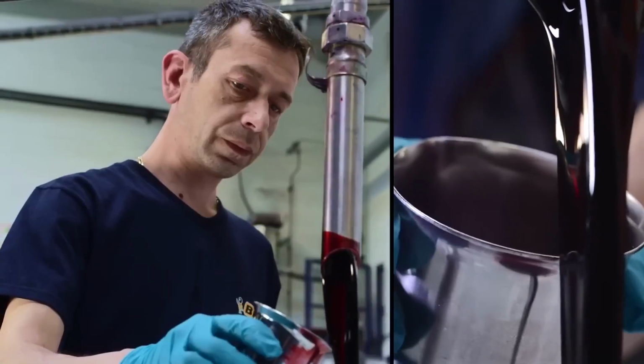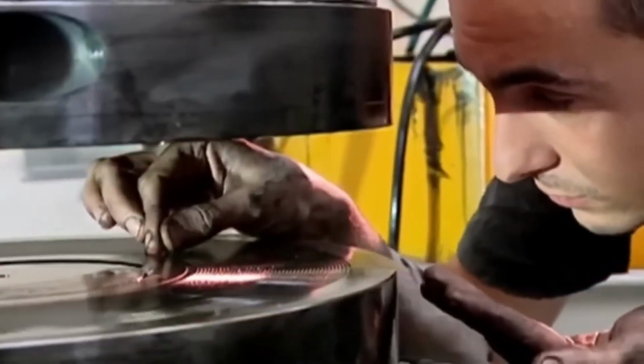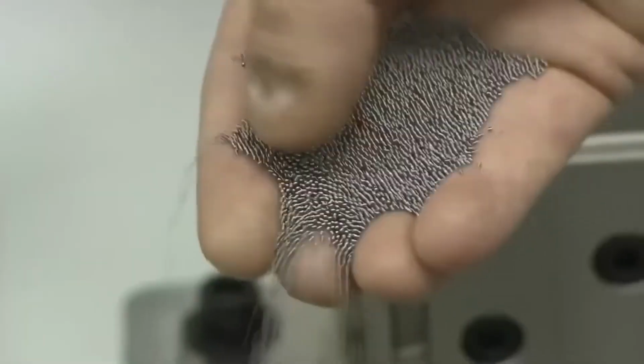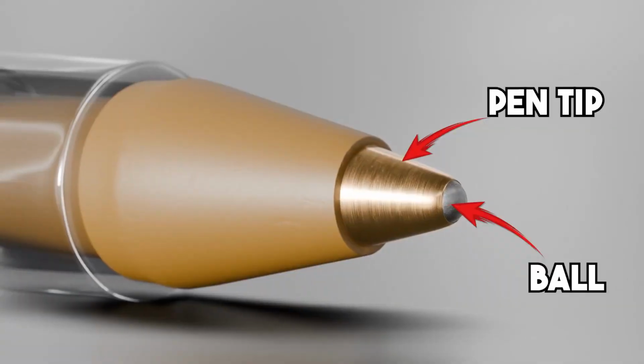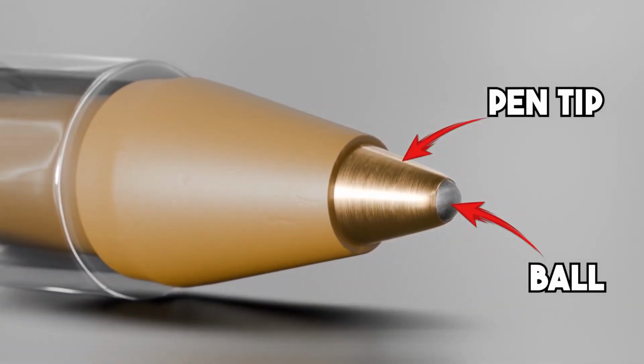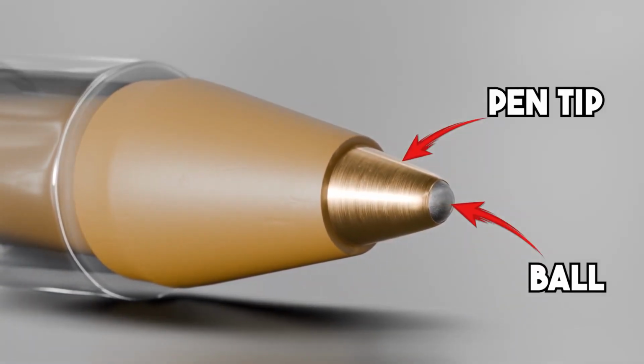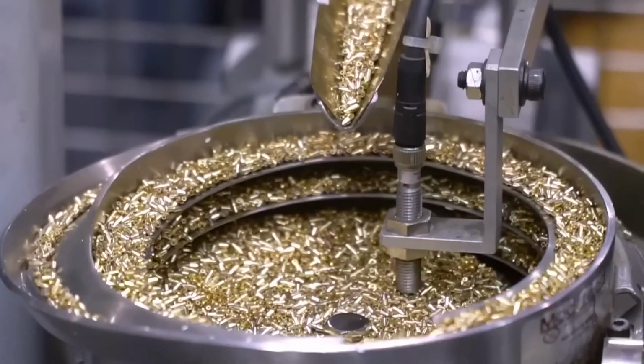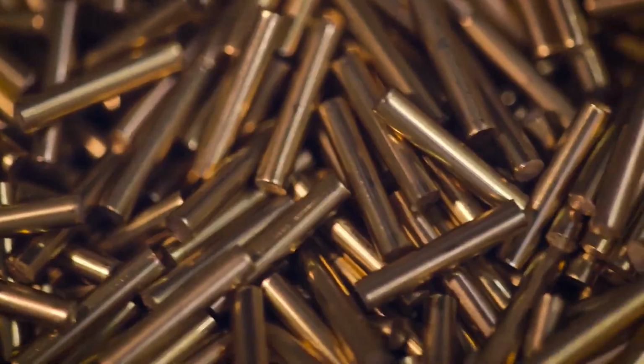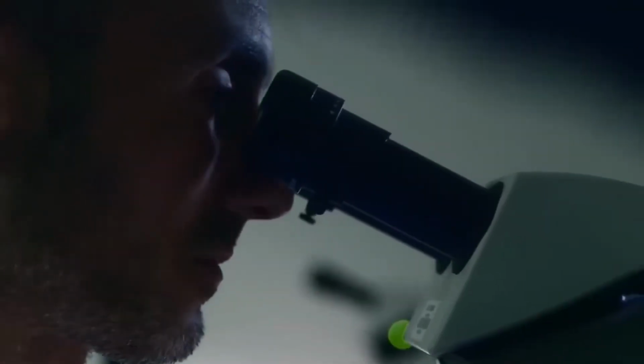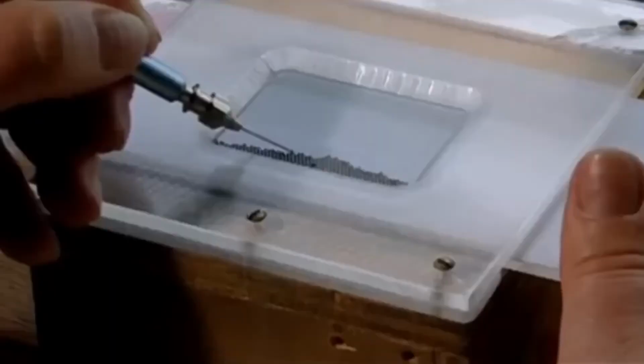The brass tip, the socket that holds the ball, is the most dimensionally demanding component in the entire pen. It is stamped from brass sheet 0.4 mm thick, then deep drawn and machined in a sequence of 5 progressive die stages. The finished tip measures 1.0 mm in external diameter at the writing end, with an internal socket diameter of 0.385 mm to 0.390 mm, a tolerance window of just 0.005 mm, or 5 microns.